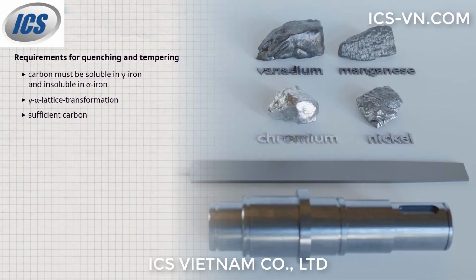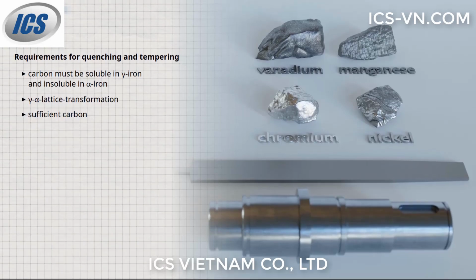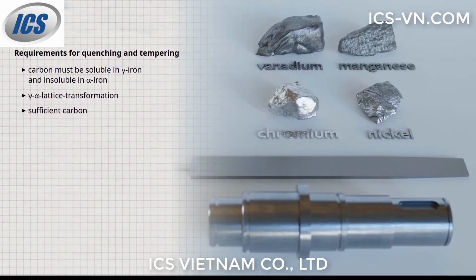Depending on the alloying elements, the steel either remains in the austenitic state up to room temperature, or the austenite phase is completely suppressed, and the steel remains in the ferritic state over the entire temperature range.